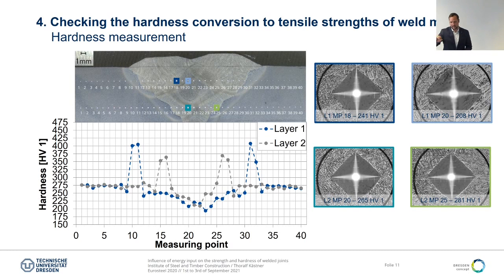I have shown some microsections here for you. The colors of the frames are representative for the positions you can see in the left picture, and we have different microstructures and therefore of course different hardness. And so what we can see is that our microstructure is not homogeneous, but we have large differences and therefore also large differences in our hardness.